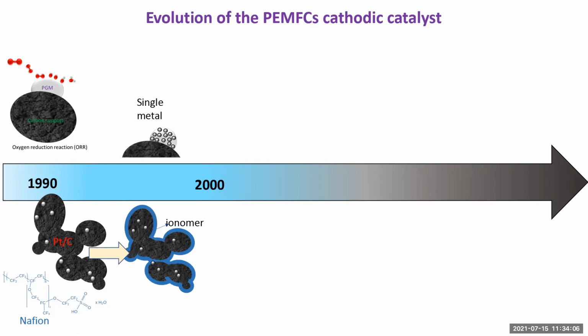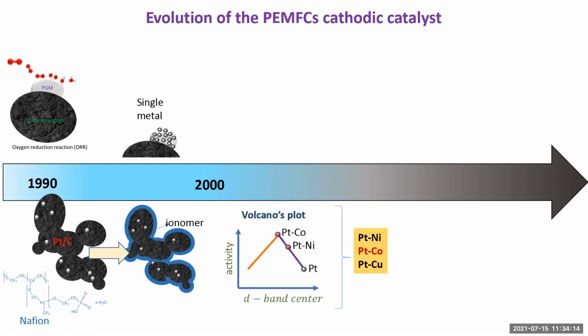The shape of the platinum particle, the size of the platinum particle, the loading of the platinum that is needed, but only based on platinum. Then, with a study of the volcano plots, it was found that if the platinum is combined with transition metals like cobalt, nickel, copper, even iron, the activity can be enhanced, so the catalytic activity can be improved.